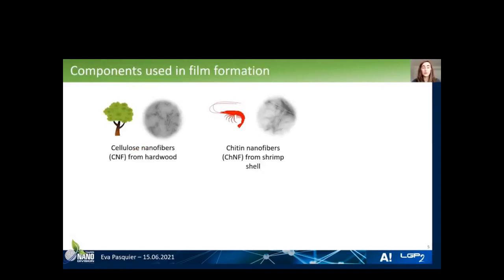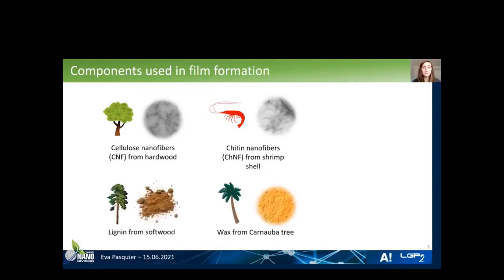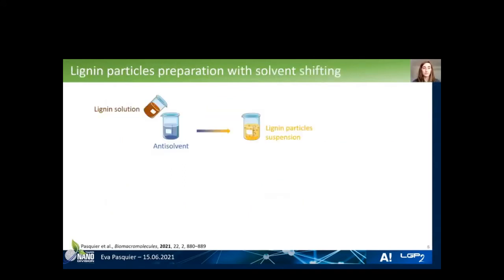And what we want to use to make it, so first cellulose nanofibers. As you all know, they can be made from wood. And we want to add some chitin nanofibers that are extracted from shrimp shells, because chitin has a positive surface charge, and this can bring better compatibility between components. Also, as additives, we want to use lignin from softwood and wax from carnauba. And this would make a 100% bio-based material, and we will use these components without any chemical modification.